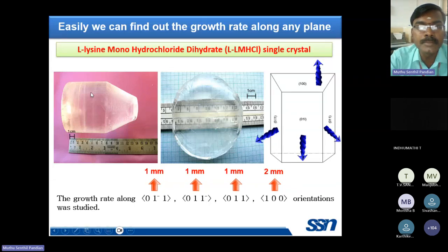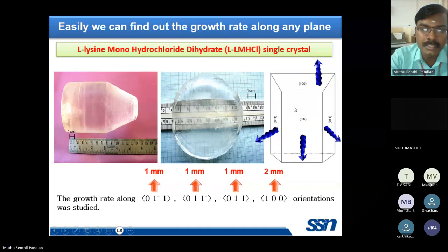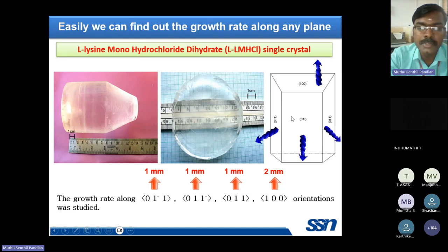So this is the lysine monohydrochloride single crystal for nonlinear optical application. This is the morphology of this lysine monohydrochloride. If you wish to identify the growth rate along different planes, what you have to do is cut the crystal along its different planes and make it a very thin plate like a seed crystal. You have to mount it at the bottom of the glass ampoule.